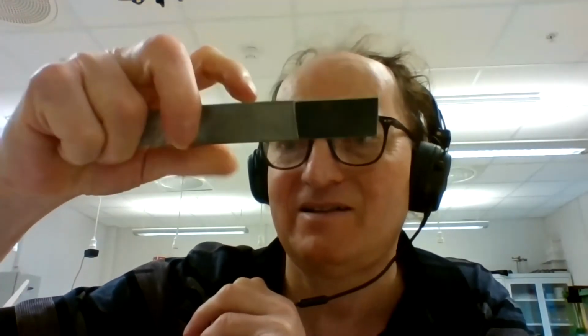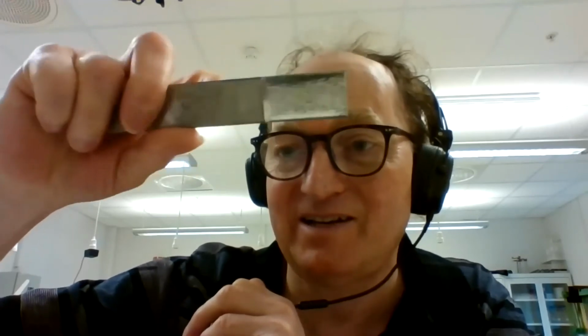And if you look carefully, you can feel, if I put my finger across here, the joint, I can just feel a difference in thickness as I run my finger across, because the base material, which has been above the electrolyte surface, this is the middle part here, is a little bit thicker than the part I've electropolished. And if I run my finger across there, I can feel a step up there, because some of the metal dissolves to give the electropolishing effect. But I think you have to agree that's really nice.